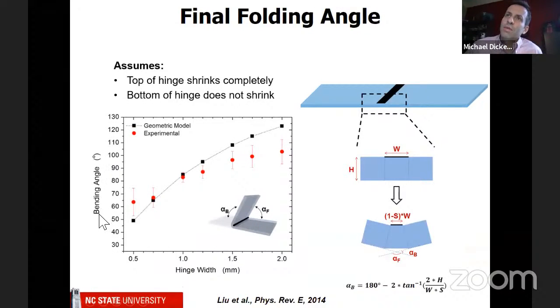And this is what we see. So this is the angle, which is defined right here as a function of the hinge width. And the black is the theoretical model, I should actually just say geometric model. It's very simple. And the red is what we actually see. And you can see that it's in pretty good agreement. We start to get a little bit of deviation around when it reaches 90 degrees, because if you imagine as this thing starts to fold like this, if it goes beyond 90 degrees, it actually will block the light from hitting the sample. And so a lot of these samples will fold to 90 and pretty much stop because the light is not reaching the hinge anymore.